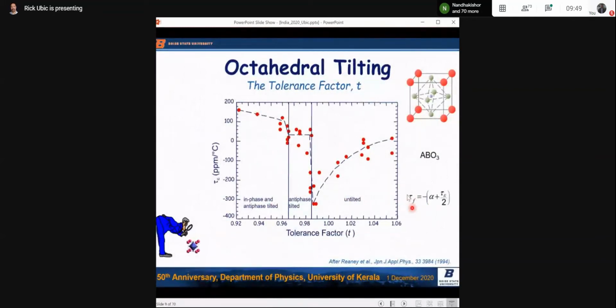Tau f is the temperature coefficient of resonant frequency. Again, you don't want this to change very much with temperature. Alpha here is the linear expansion coefficient. So these are related. Tau epsilon and tau f are related through the expansion coefficient. So that's how the tilting affects properties in a generic hand-wavy sort of way.